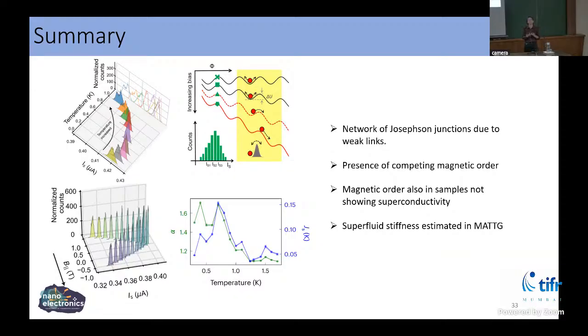And that itself is interesting because the general sense for superconductors is that superconductivity and magnetism do not go hand in hand. This magnetic order is also seen in samples that do not show superconductivity, telling us that the system hosts this magnetic order over a larger range of twist angles. And in a small last part, I told you how we have estimated the superfluid stiffness in this system.